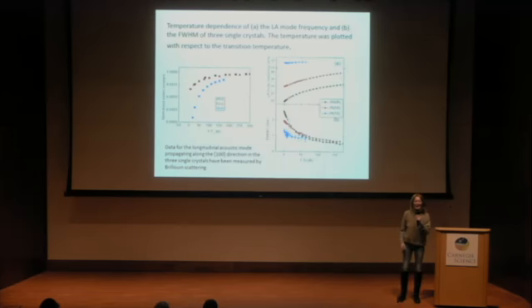conclude, it is obvious that the A site in the perovskite plays a fundamental role for the dynamics and also for the phase transition, just opposite to what one would expect if you know that p-d hybridization effects are driving a polar instability. Thank you for your attention.